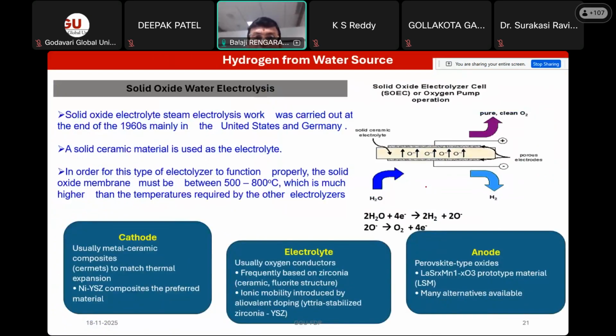And coming to high temperature solid oxide water electrolysis, you have to do this electrolysis at 500 to 800 degrees Celsius. So most of the material has to be stable. If you want to identify a material which should be stable in water as well as at high temperature, the only choice you have is ceramic based material. If you go with a ceramic based material, whether it is an electrode or a separator, then obviously the electronic conductivity is one of the key challenges. It has a low electronic conductivity, but it will be stable at high temperature.